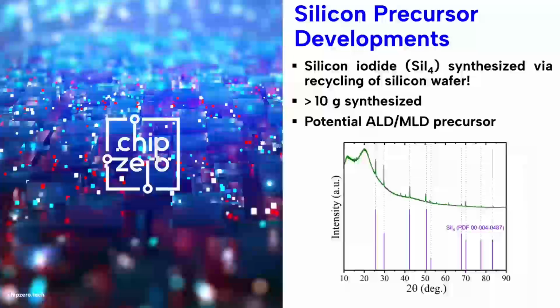Another important achievement this project has already delivered is the development of silicon iodide. We know that we waste several hundred thousand silicon wafers every time. So how to recycle this silicon wafer? That is very important. Here, in this innovative approach, we were able to utilize this silicon wafer to develop a new, not new, silicon precursor, silicon iodide. And we even synthesized this precursor in more than 10 grams. We also tested the silicon iodide precursor for ALD.